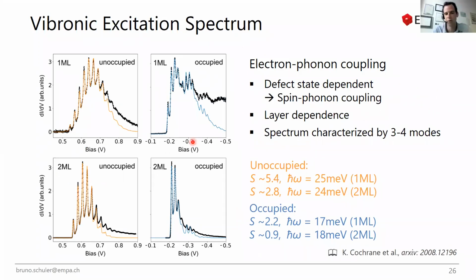So this is on the order of, in the case of 2 monolayer, about 200 femtoseconds. If you just think about the distance between the defect states and the graphene, and you model this by just a vacuum, that's more or less what you would expect. You would probably expect a bit longer lifetime, so we are not sure ultimately if a fraction of our broadening still comes from coupling to low energy acoustic phonons.